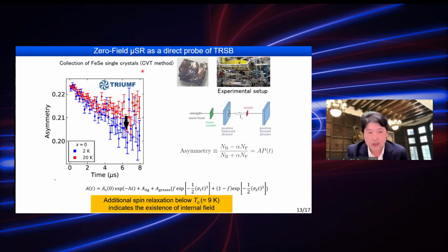To address this issue, we have measured zero field μSR, which is a very sensitive probe of the magnetic field inside the sample. This can be used as a direct probe of time reversal symmetry breaking.